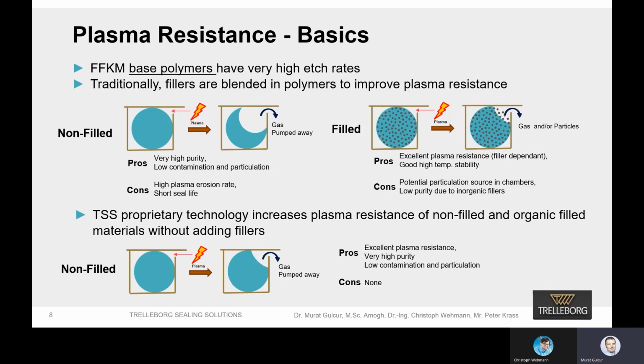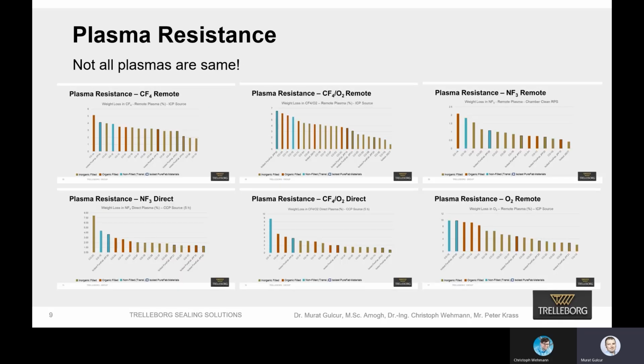So in Trelleborg Sealing Solutions, we developed a new technology. By using that technology, actually we can improve the plasma resistance of a non-filled material significantly, without adding any fillers, and therefore we have all the advantages of non-filled materials, like having high purity and low contamination, and we eliminate all the concerns about high plasma erosion rate and short seal life, which I'm going to show the results in the next slide.